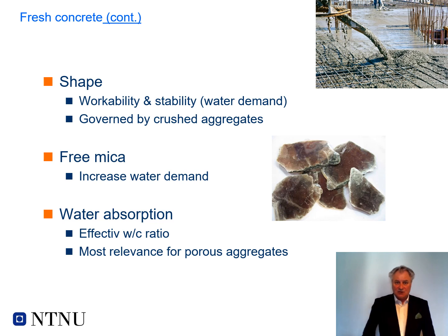In some Norwegian rock types, we do have a lot of mica minerals. Mica minerals like biotite and muscovite are very, very flaky minerals. So when you start to crush down your bedrock, particularly into manufactured sand, you could increase the content of free mica. When the mica is inside the particle, there is no problem. But when you start crushing free mica, the free mica particles will have a very high specific surface area because they are very thin, flaky minerals. Those thin flaky minerals need more cement paste to cover them. So free mica is a problem in manufactured sand, and it will increase the water demand, and it will make the concrete stiffer and less flowable.